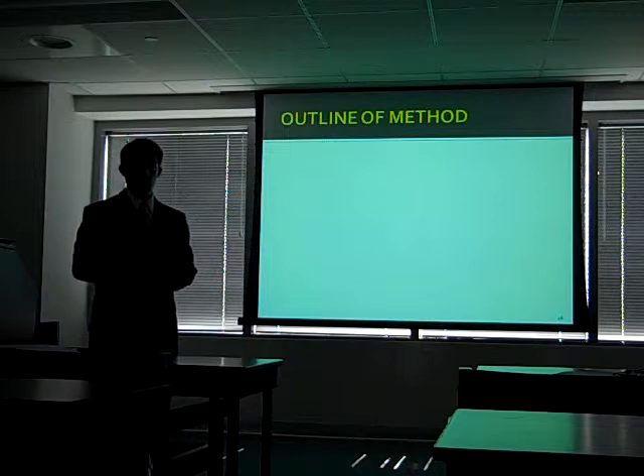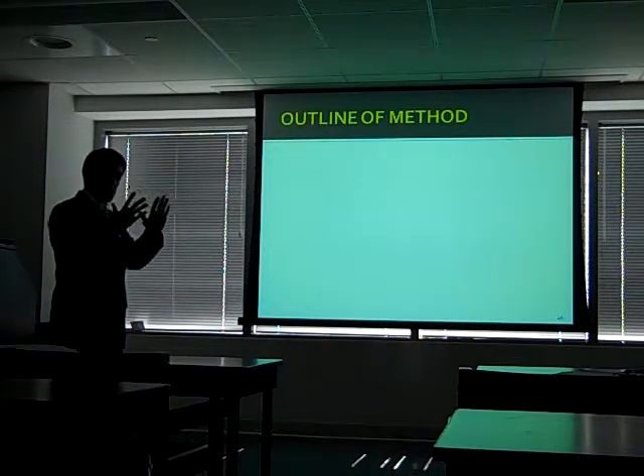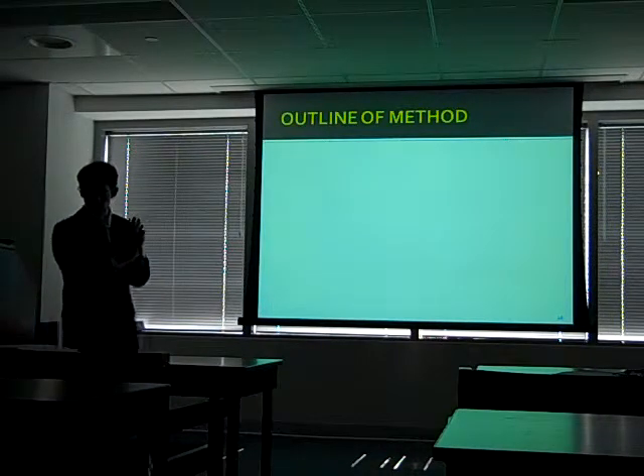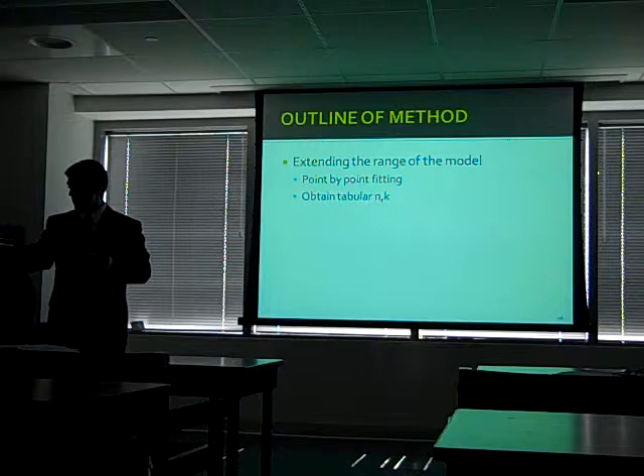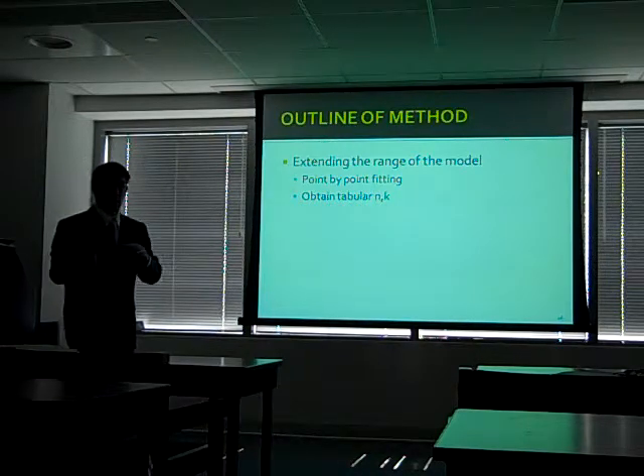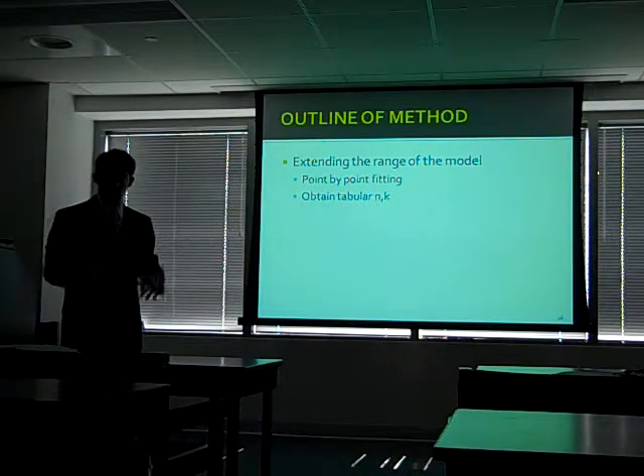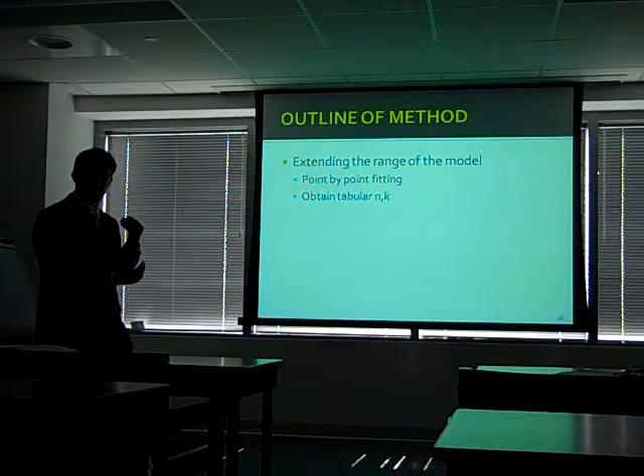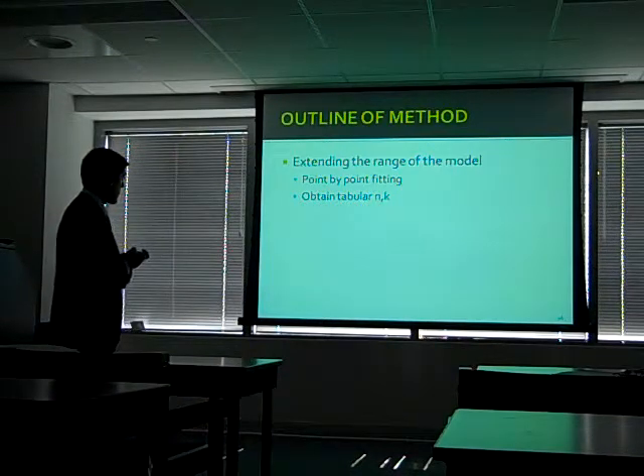So now that we've done this Cauchy analysis, we know with confidence the thickness of the film, and we have an initial guess for the optical parameters in a certain spectrum of the data. So now we want to extend the range because we want to model the band gap, and the band gap is around 350 nanometers. It's not in that transparent region.